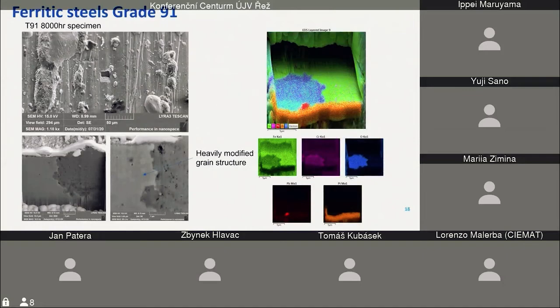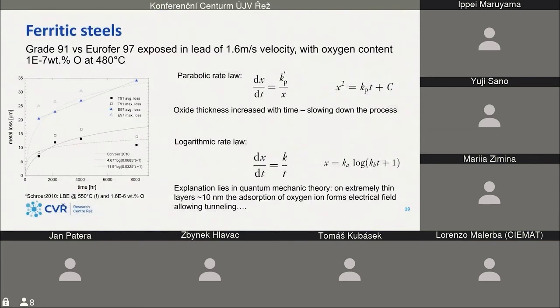So we took a closer look at this specimen, and you can see that in chemical composition there is no difference. There is a cross-section between the unattacked place and a place where magnetite developed, and the only difference is fine grain and heavily modified grain structure, but there is no difference in chemical composition. So if we take a look at how fast material is lost, there are two theories for that.